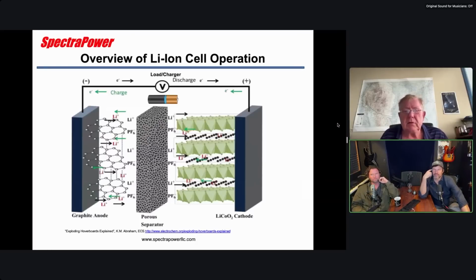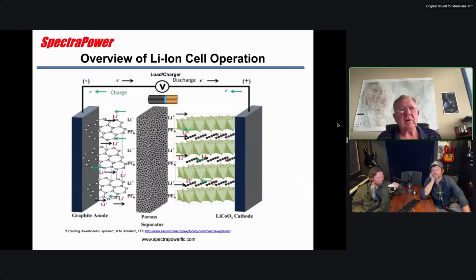There's a controller. Yeah, so you typically will specify the C rate that you're going to charge at. So if you're say a 1 amp hour cell, which, in your cell phone, you've got about, I think 3-4 amp hours if I'm up to speed these days, you're going to charge it typically at one half C rate. So maybe it's a 2-hour charge. If it's a laptop and it's a high energy cell, your laptop takes longer to charge typically, right? It's more like 4 or 5 hours. And the reason is that it's at a lower rate because you have a high energy cell.